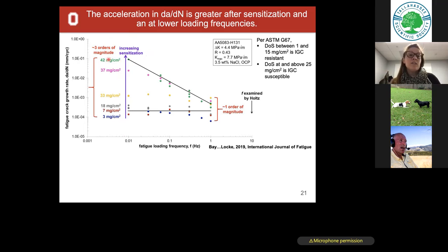And in fact, these values in the lab, depending on the temperature you use, we can get in about 30 days or so. In Hawaii, they can reach these values. They had a ship sitting out in Hawaii just to see what would happen, and they saw these values in about 10 years. In about 10 years, a ship would experience theoretically 3 orders of magnitude acceleration in its ability to grow a crack. And so this was a big finding for us to say, hey, you do have a really egregious effect of sensitization on your corrosion fatigue properties and likely a cause for some of these cracks that you see.